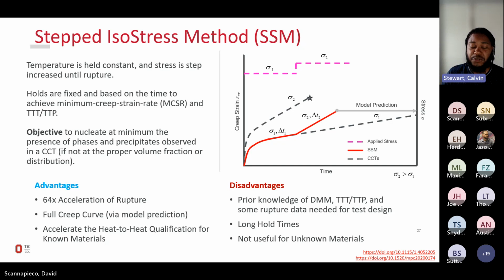Now, if you want to know the span of service conditions, you need to do multiple tests at multiple combinations of stress and temperature in a basement somewhere and wait many years to get your data. With the stepped isostress method, instead of doing that, we hold temperature constant and we dynamically increase the load to create a test that will fail sooner. We design our test matrix based on deformation mechanism maps, time temperature transformation, and precipitation, to try to nucleate at minimum the presence of the right phases and precipitates. And by doing this process, using a well-posed model, we're able to predict the conventional response of the material. We're actually able to extract multiple curves of creep information from a single test.